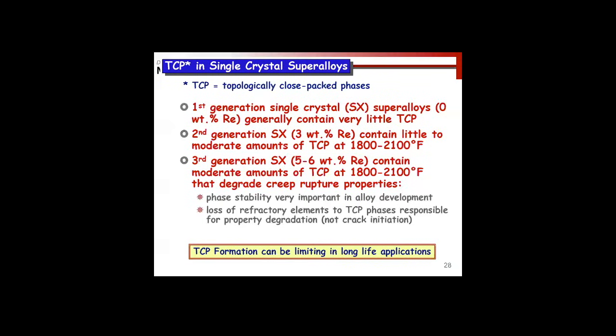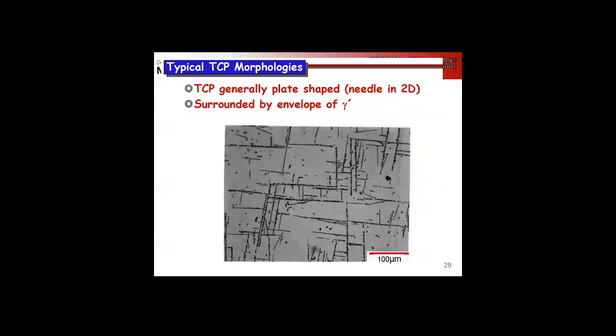So we suck out our refractory phases to form these topologically close packed phases, and in blade alloys they form these needle-shaped structures surrounded by gamma prime. So this gray here is gamma prime, and these dark phases are TCP structures.